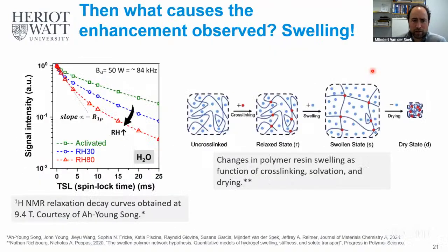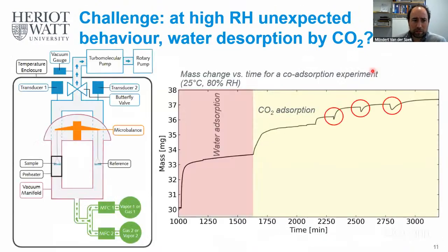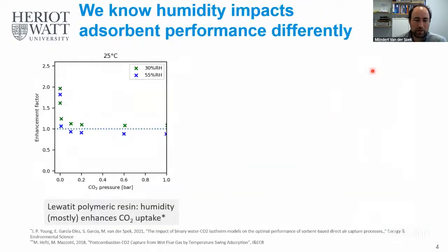And okay, now I need to jump right back to the very first slide. I'm going to do it. Hold on. This one. That also explains why the enhancement is really only observable in the very low CO2 partial pressure range, because at higher CO2 partial pressures, the CO2 itself will have solvated the material already. So the presence of water doesn't help anymore, because the CO2 will have already blown up the pores. So this is our current understanding. And the nice thing about science is that a paradigm is true until a new paradigm presents itself. So it may well be that we're proven wrong in a couple of years from now. And we'd be happy to, because that only means that science has further advanced. But this is how we believe that the water helps the CO2 adsorption at this moment.